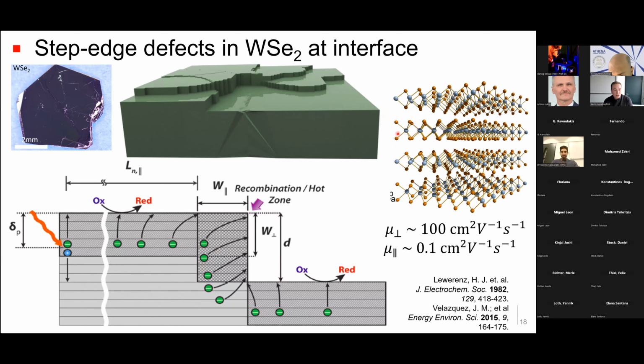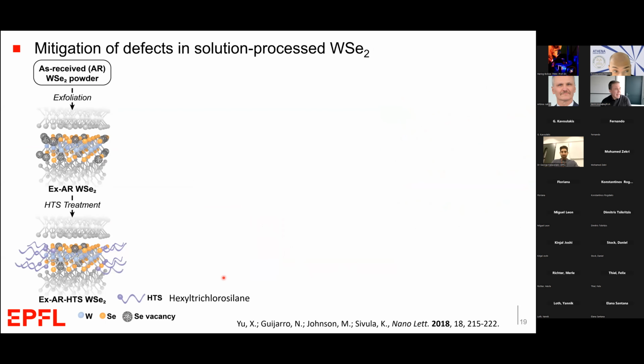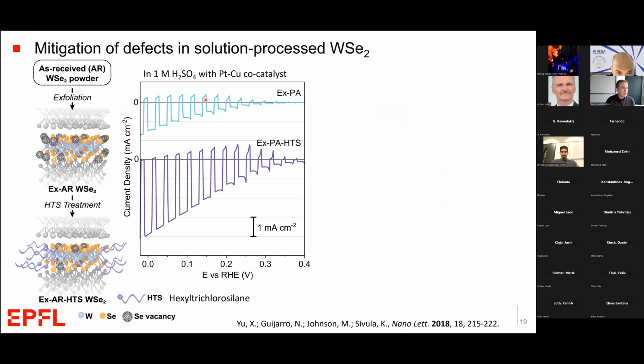Again, the charge carrier transport in this direction along the flake axis is about 1,000 times greater than it is in the direction parallel, which means that photogenerated electrons are more likely to travel very fast towards these edge sites and recombine. So in order to reduce this recombination, we later developed a passivation technique using an organic hexyltrichlorosilane, which can plug some of these selenium vacancies. And this led to improved performance for hydrogen evolution. That's shown here. This is without the HTS treatment, and with the HTS treatment, we've improved the photocurrent by about a factor of 4. Now we're getting about 4 milliamps per centimeter squared photocurrent for hydrogen production out of these electrodes.